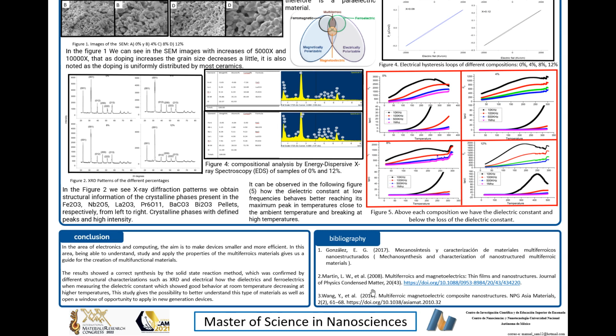We can conclude that in the area of electronics and computing, the aim is to make devices smaller and more efficient. Being able to understand, study, and apply the properties of multiferroic materials gives us a guide for the creation of multifunctional materials. The results show a correct synthesis by the solid state reaction method, which was confirmed by different structural characterization such as XRD and electrical measurements, measuring the dielectric constant, which shows good behavior around room temperature, decreasing at higher temperature. These studies give the possibility to better understand this type of material and open a window of opportunity to apply it in new generation devices.